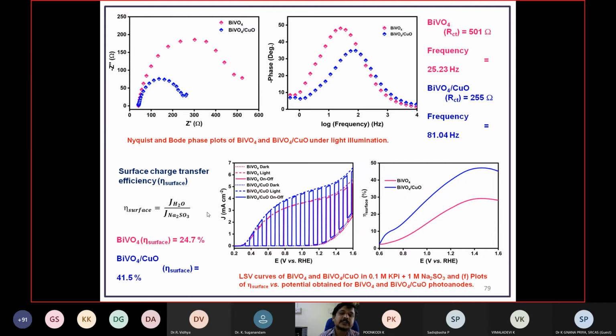Then the surface charge transfer efficiency we have also estimated by using sodium sulfite as a sacrificial donor. From that, we have done linear sweep voltammograms under dark condition, illuminated condition, chopped condition, everything. Finally, we obtained an enhanced charge separation efficiency of up to 41% for the heterojunction, nearly 1.8 times higher compared with bare bismuth vanadate.